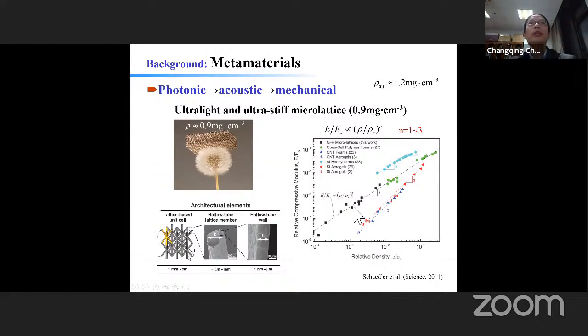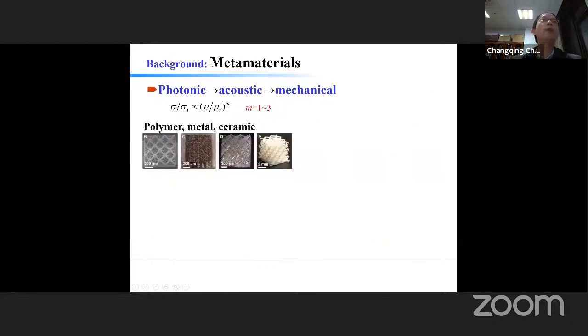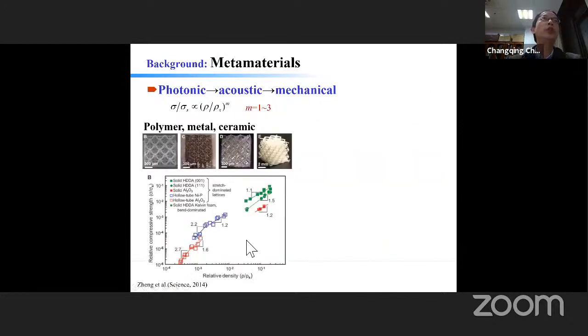For all the other bending-dominated materials like foams, you expect n to be about 3, but for this micro-lattice, you can see n is about 2, or n will go to 1. So that means it's a very stiff micro-lattice. In addition to stiffness, people are also able to produce very strong micro-lattices.